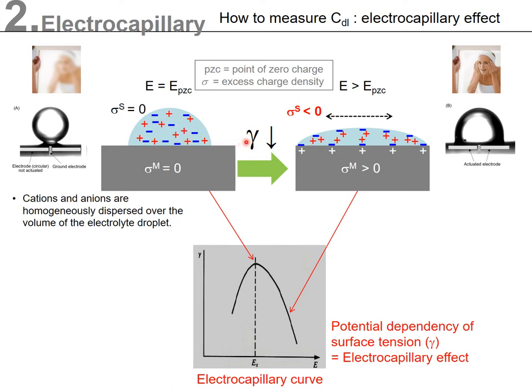However, after we applied a potential to the system, the surface tension went down because the droplet is dispersed along the surface of the electrode. It means surface tension is going down, or the wetting property was improved by applying a potential.